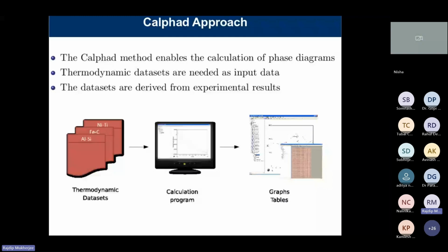And software like Thermo-Calc, OpenCalphad or Pandat, all these have student versions also, where you can get defined databases like aluminum, silicon, iron, copper, nickel, titanium. All these databases you can load in the software in the calculation program. And then you can get graphs and tables. Graphs and tables means you can get the phase diagram, you can get the free energy diagram, and free energies as a function of compositions, right? So it is very important: if you can learn this CALPHAD approach, then you have a good understanding of the phase diagram and the free energy diagram of a system.